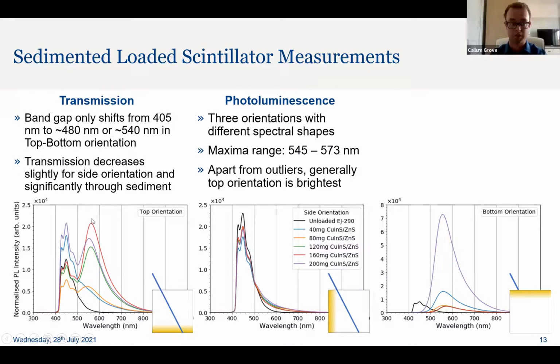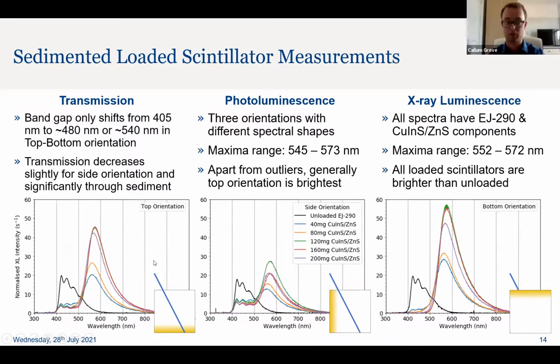And then photoluminescence for these samples. As you can see, for the top orientation and the bottom orientation, the quantum dot peak is now significantly brighter than the unloaded scintillator. And that carries through to the X-ray luminescence, where we have quantum dots absorbing the unloaded peaks and producing a reasonably high emission, which is also significantly higher than an unloaded sample.